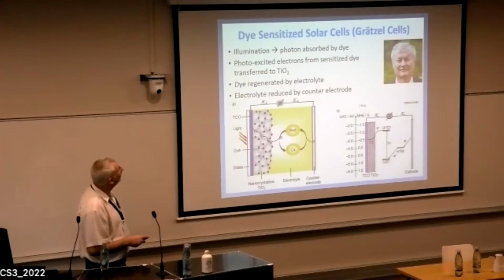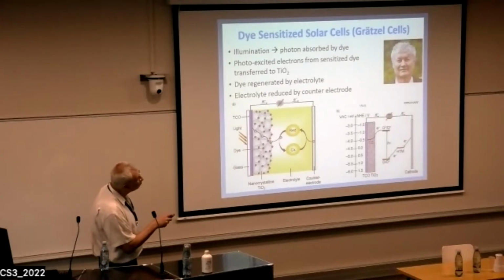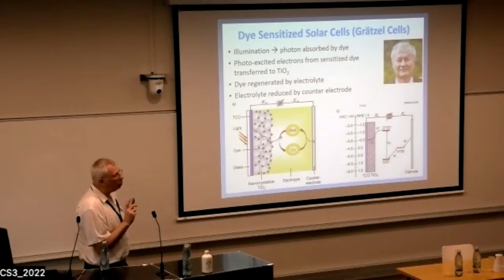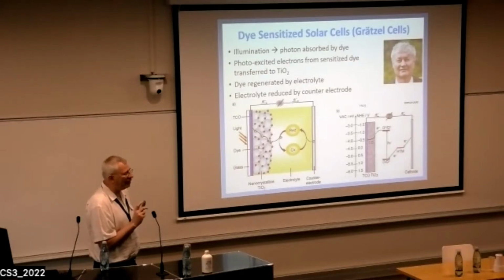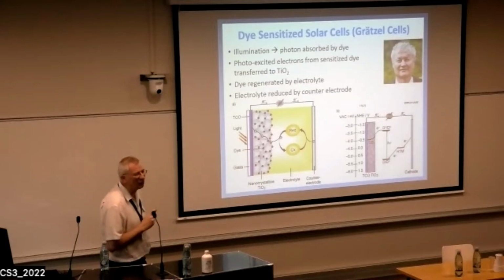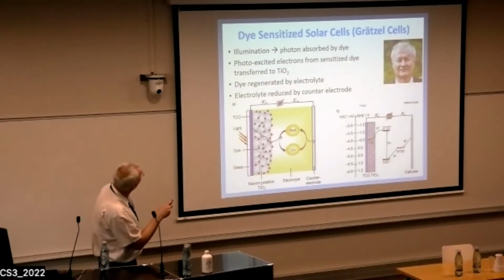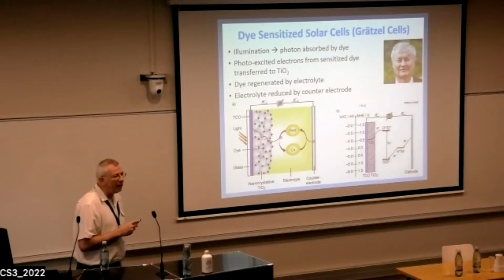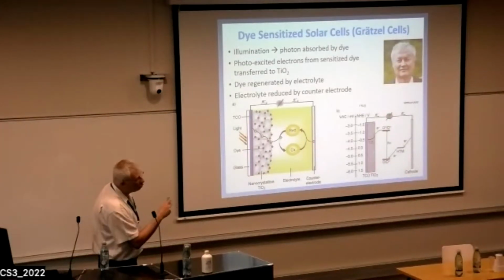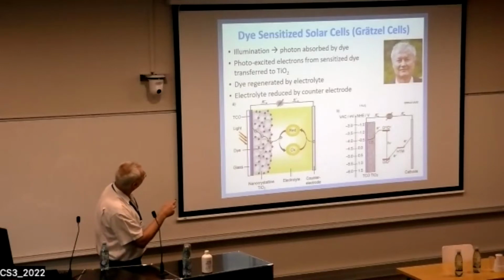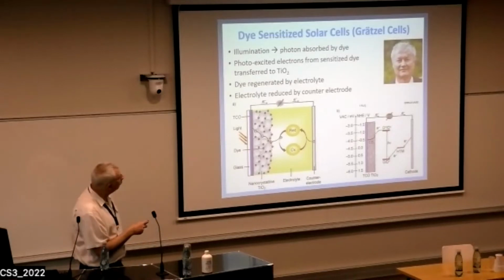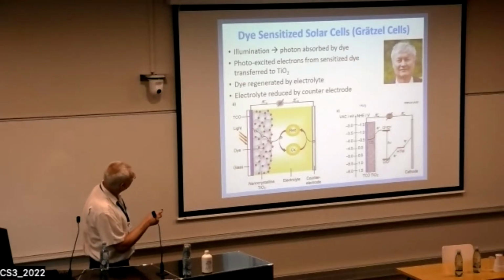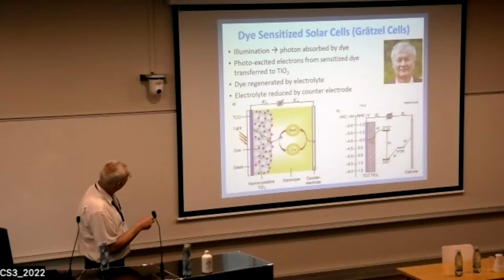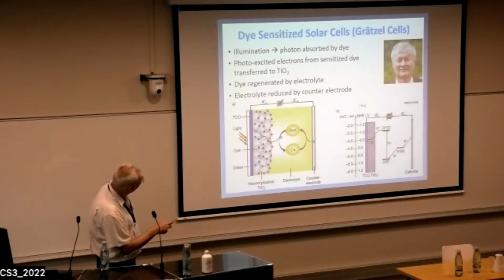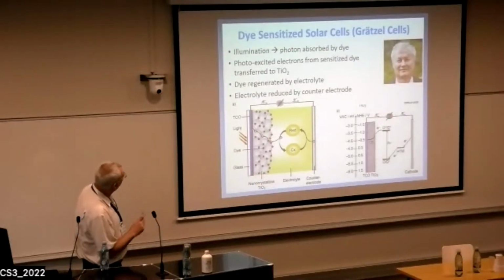So we started with the dye-sensitized solar cell, also known as the Grätzel cell. So this is Michael Grätzel. He has one paper which was cited over 35,000 times, the paper in which he actually described this solar cell for the first time. And these cells are based on a dye, and the dye basically absorbs the light. So you illuminate the dye, you absorb the light, and you photo-excite it. The electron is transferred to a titanium oxide layer, which is shown here. The dye is regenerated by an electrolyte, and the electrolyte is reduced by the counter cathode. The electrolyte is typically iodine or something like this. And these are the energy levels. And these are well-known cells.